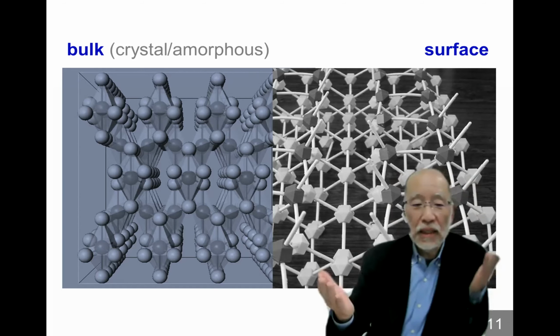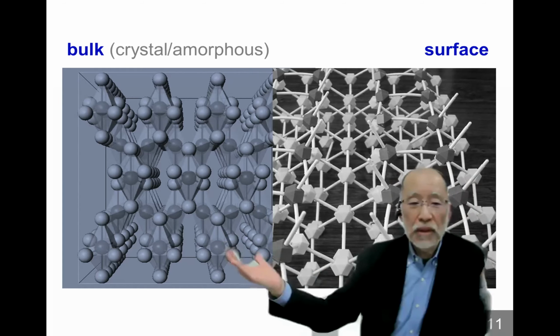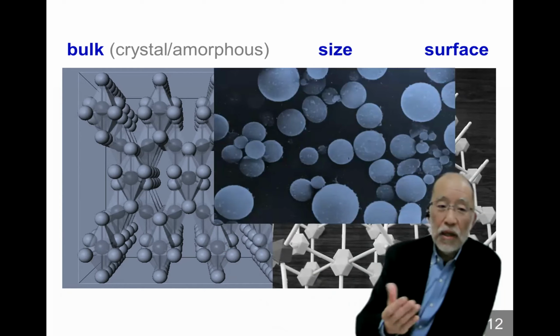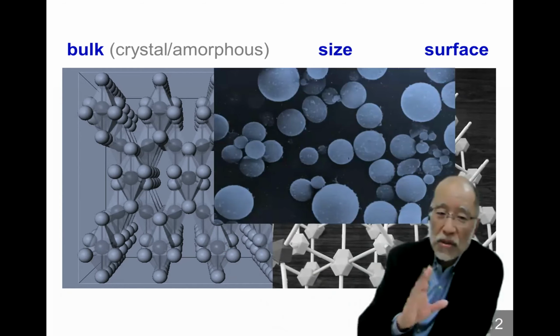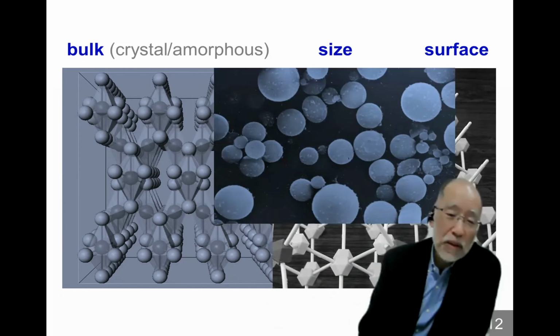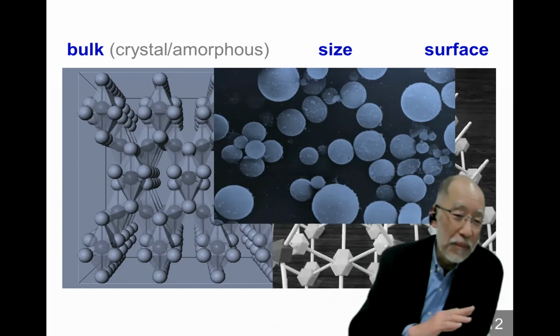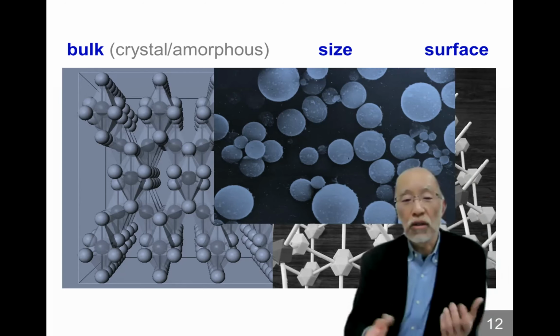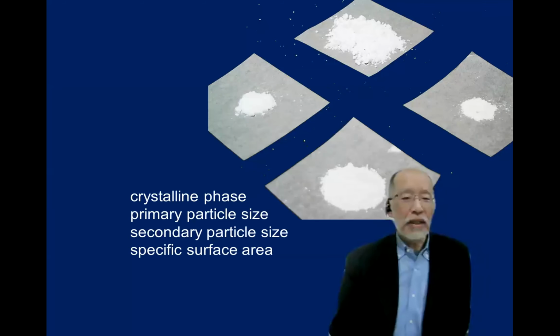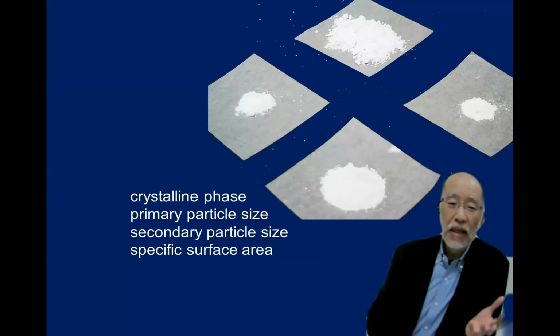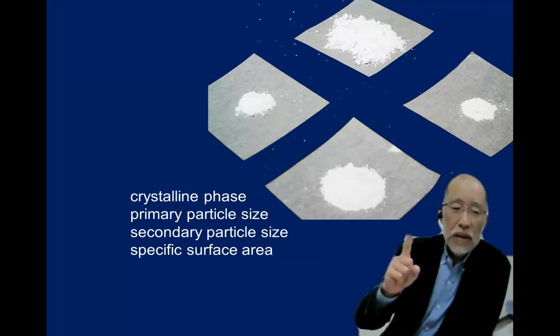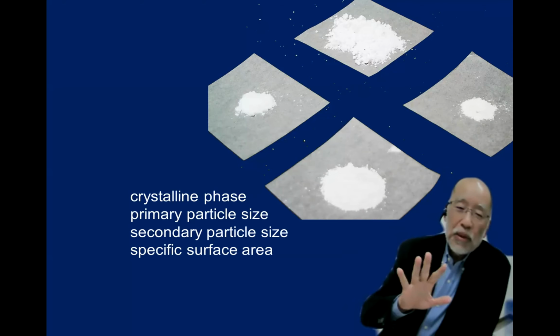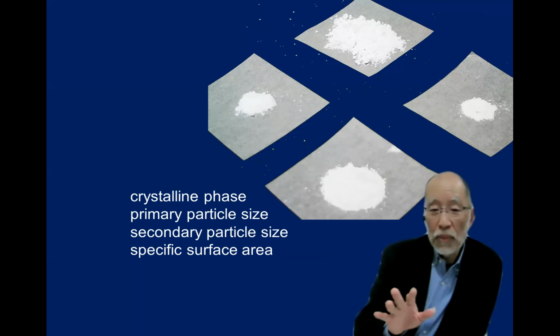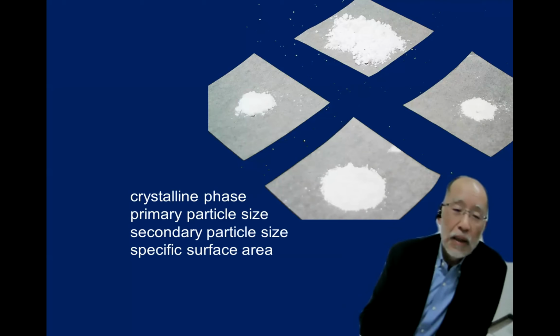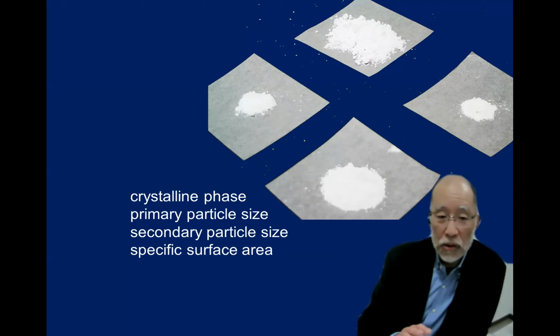And even if we can determine the bulk and the surface structure, still we need to determine the size. And of course, you know that the size has some distribution, not uniform. So therefore, it is very, very difficult to describe the structure of solid materials. So then, what we can measure as a structural property is crystalline structure, primary particle size, secondary particle size, and specific surface area. Well, probably no other conventional comprehensive method for analysis of solid structure.